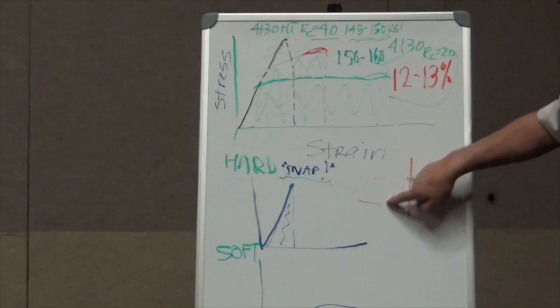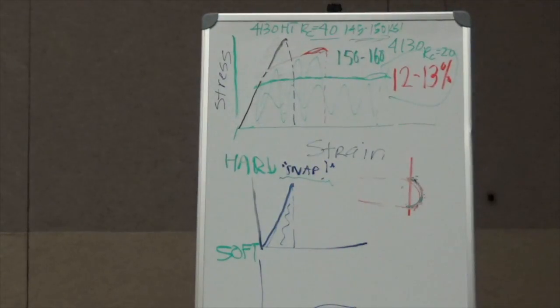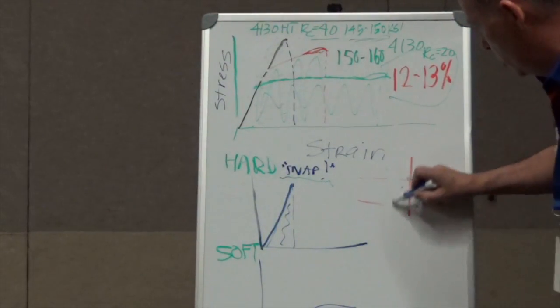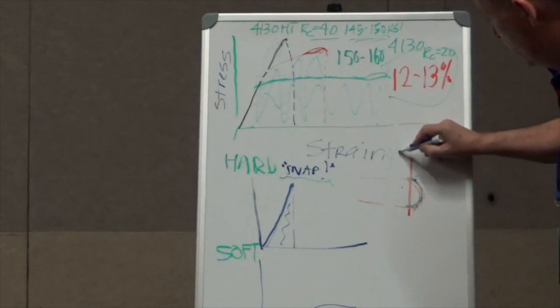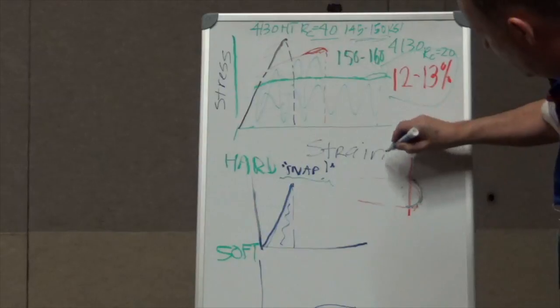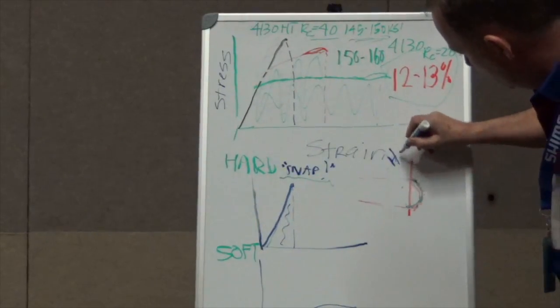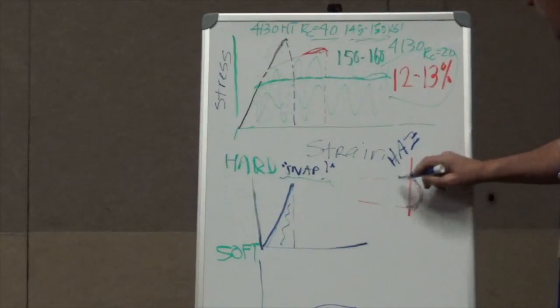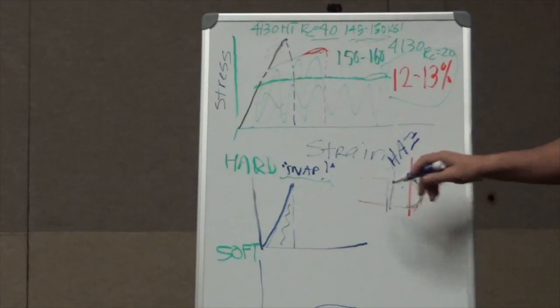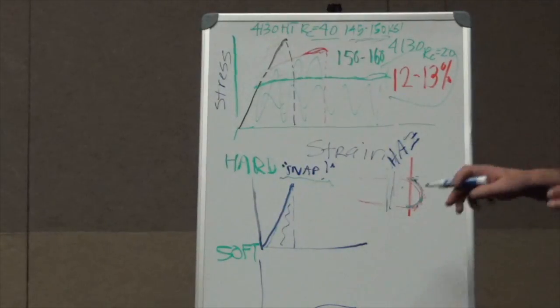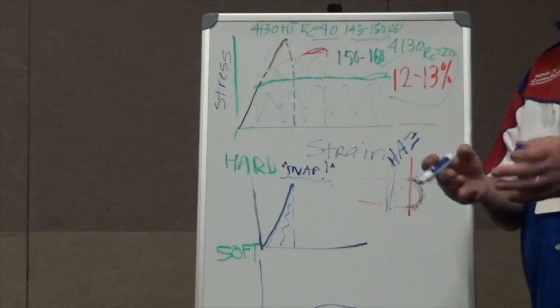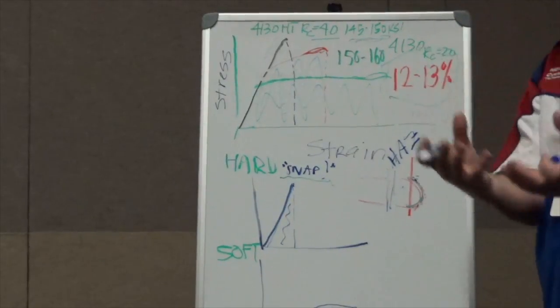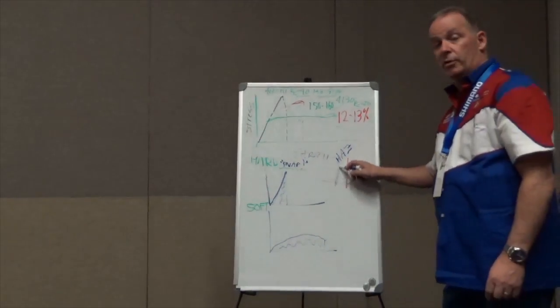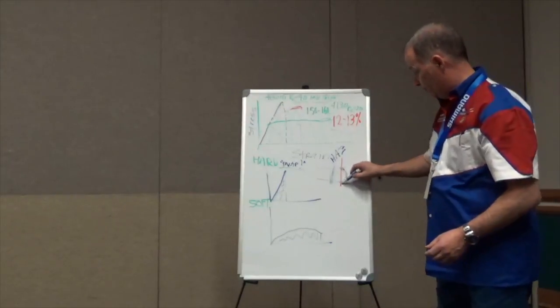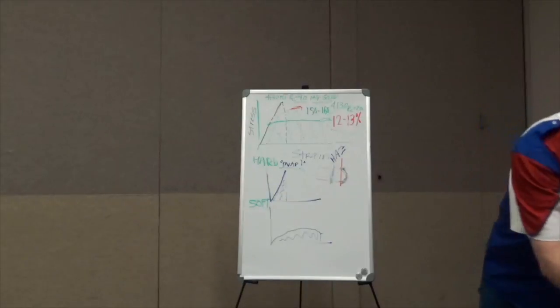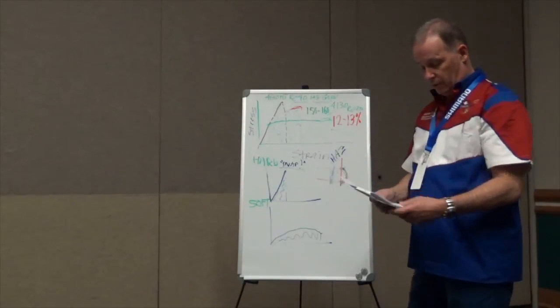By the time you get back to where you would see your typical heat-affected zone lines where you join a tube, so-called HAZ, I don't know if you can see that. I'll see if I can write it to where it can be seen. Heat-affected zone. Out here where the heat-affected zone is, by the time you get out that far away from the tube, and it's not very far, the stresses are very evenly distributed around the radius of the tube. It's a radial distribution. The tubes do not fail here, even though they're softer. They just don't. They fail here. So the idea there is that there are some specific things that you want tubes to do.